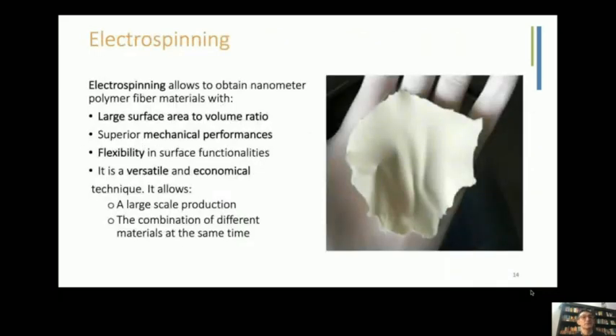So this combination of gelatin, keratin, and glycidoxypropyltrimethoxysilane was, because our aim was to develop a skin model, extruded using an electrospinning process. Why the electrospinning process? Because if we want to produce a skin structure, it's important to reproduce the typical micro and nano features that compose the extracellular matrix of the skin. Moreover, it's a technique that is able to produce a large surface area to volume ratio.